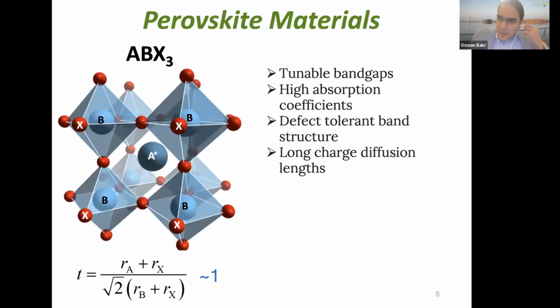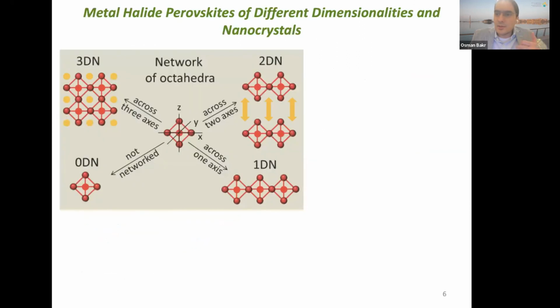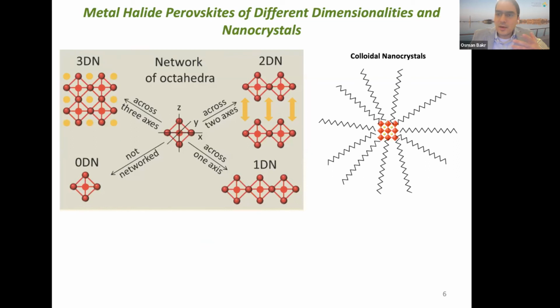These materials have tunable band gaps, very high absorption coefficients, they're very defect tolerant, and the charge carrier diffusion in these materials is long. In addition to traditional perovskites, if you start making the A cation large, you start breaking up the perovskite network, and then you could start forming very interesting two-dimensional materials, for example, or zero-dimensional materials, or one-dimensional materials. And even if you start using surfactants, you could start creating nanocrystals and quantum dots.